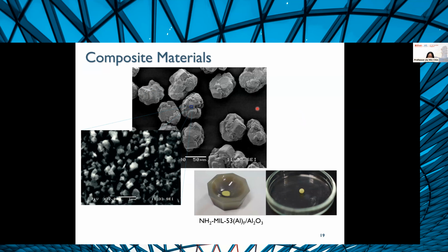So we used, in this case, gamma alumina again, but in the form of particles instead of AAO membrane. And we found that we could grow these MOFs onto the surface of the gamma alumina. And my students did some fluorination, and they ended up with this yellow MOF powder, which is very hydrophobic. They like to have some fun in the lab, and these were some high school students. So they were playing around with some water droplets on this powder, and they dropped a drop of water and rolled it around, and they found that the powder ended up encapsulating the drop of water when you roll it around in this powder.